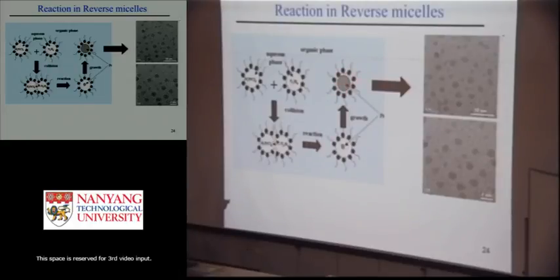Right now, this nanoparticle actually is not protected by the surfactant, although it is located in the water droplet. So without removing the droplet, without removing the surfactants, the nanoparticle is stable. But if we do some centrifuging and washing, you remove the nanoparticle from the droplet and the surfactant environment, and the nanoparticle may easily agglomerate because its surface is clean, with no protection.